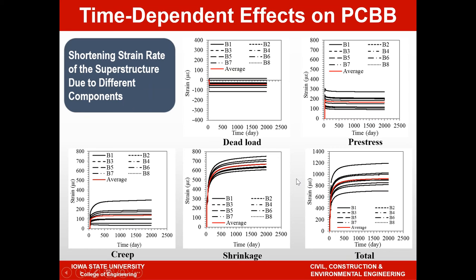I know we're showing a current practice at 525 strain, as I mentioned before. This is not necessarily correct because the current practice of 525 subtracts out some pre-stress strain as well as some other effects. So we're actually in discussion with Caltrans right now to make sure that we reflect their practice more accurately. But one thing is clear: the current practice does assume a constant strain rate, and you can see that the bridges show different strain rates based on what we might model.